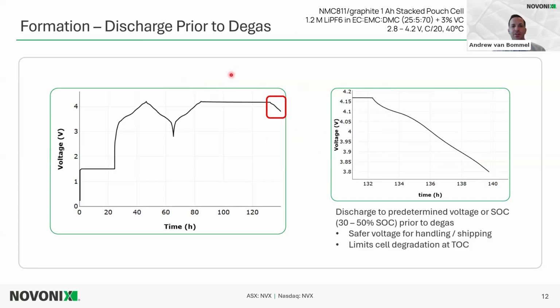So after that important top of charge rest step to get that voltage drop, then the cells are discharged to a predetermined SOC, a predetermined voltage. This one was just discharged at 3.8 volts. The reason it's doing this, one, it limits the cell degradation. There's more degradation at higher states of charge. And then often if we are forming cells and sending them to our customers, it brings them to a safer SOC. That would be around 30% SOC would be our standard.